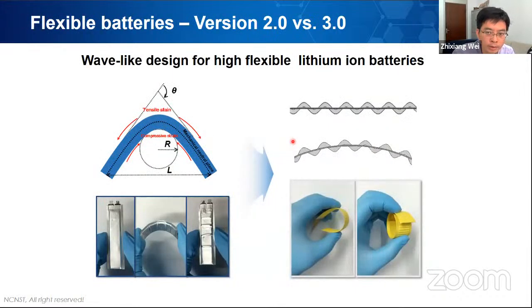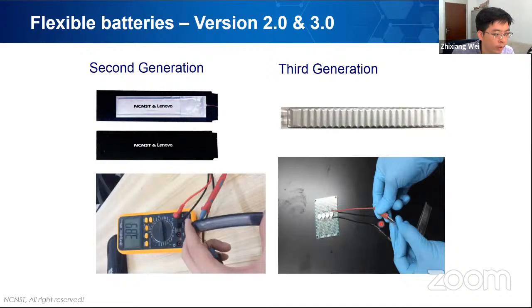But if you make the battery thick enough, normally there's some problem with the mechanical properties. For example, in thick films, if you're using this kind of material, because the outer side is under tensile strength and the inside is under compression strength, there will be some cracks on the inside surface. Therefore, we designed these wave-like structures and found that they are really good for showing this kind of flexible battery with high capacity. This is the real image.